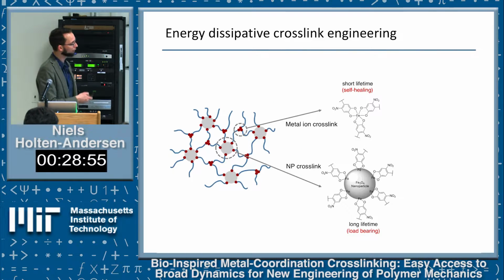We've begun making these hybrid networks where we have both metal ions, indicating a metal ion crosslink structure, and nanoparticles in the same network. The metal ion crosslink structures are short-lived, so fluid-like, while the nanoparticle crosslink structures are long-lived and much more solid-like. This should give us load-bearing properties as well as dynamic self-healing properties built into the same material.